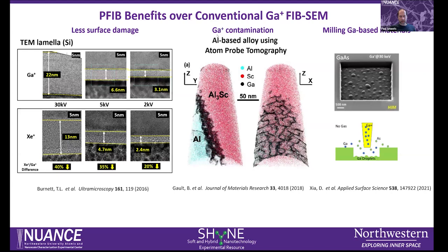Another issue that could arise with a gallium FIB-SEM is with specific classes of materials, like aluminum. This is atom probe data, where every dot represents an atom. We have an aluminum scandium alloy grain structure here that's adjacent to an aluminum structure, and you can see in black the gallium atoms that are segregated to the grain boundaries.